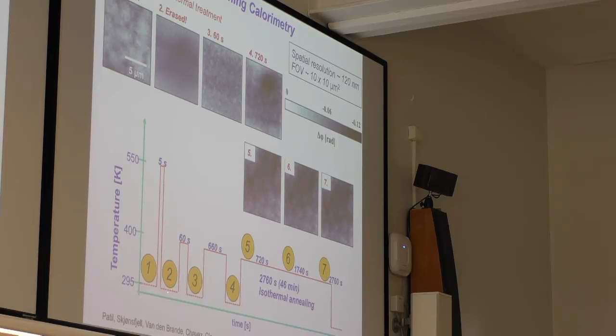And then we could measure the structure again, and you can see that the structures have been erased, right? So this is now the polymer structure, which has been up in the melt. Of course, in the melt, all the morphology is sort of blurred out, disappearing, right? And then by going snap back to room temperature, it's quenched. So it's a quenched state, basically. And then we can, for example, go up to this annealing temperature, just short of 400 Kelvin here, for say 60 seconds. And you can see that